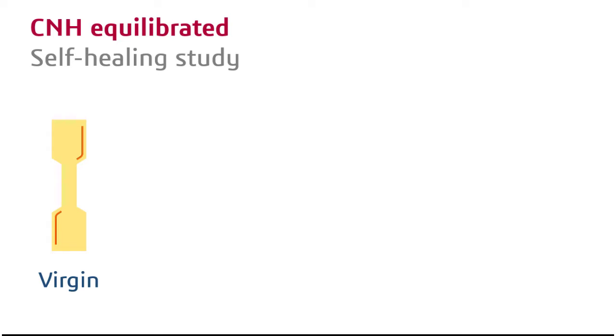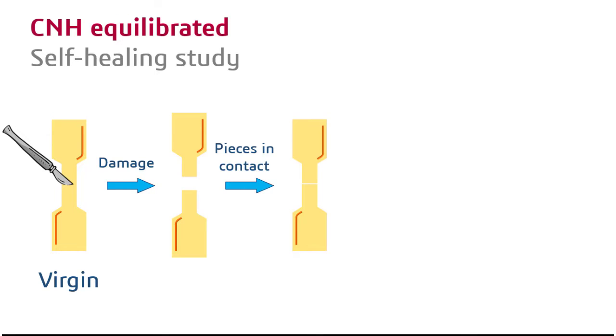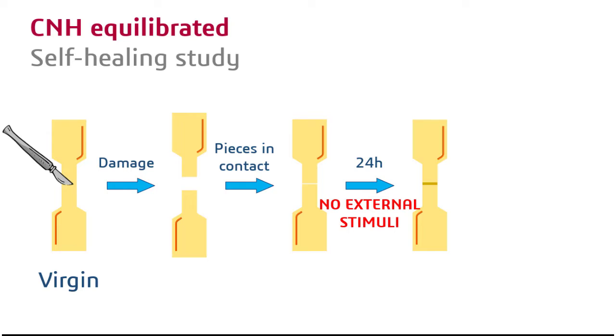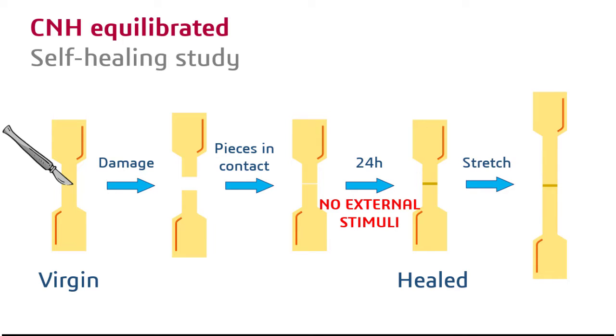Firstly, non-damaged virgin hydrogels were cut into two different pieces. Then, these two pieces were aligned and put together. After 24 hours, without any external stimulus nor adding any agent, just leaving the pieces together under ambient conditions, the two pieces rejoined, becoming a unique material again, named healed sample. Lastly, these healed samples were stretched to obtain their mechanical properties and compare them with those of the virgin specimens.